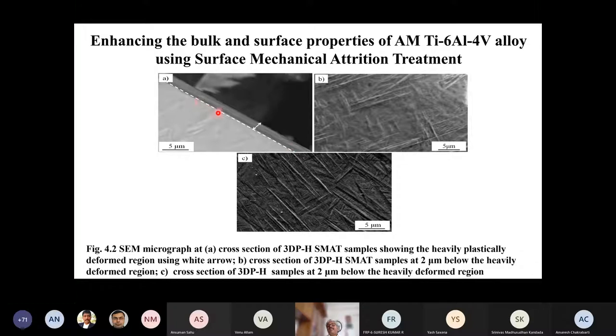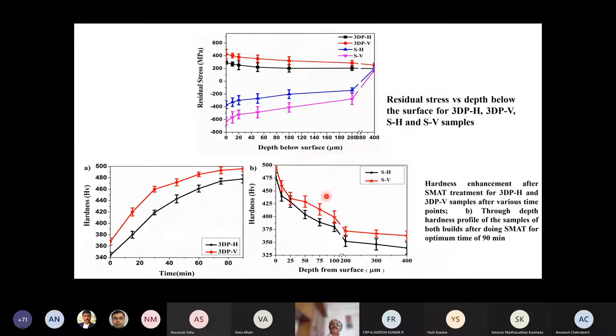And remember that additively manufactured materials are characterized by generation of cracks from the porosities, right? The coalescence of porosities leads to generation of cracks under loading conditions. So in this case, we closed the pores at the surface. Therefore, the cracks which would have generated at the surface were substantially minimized, and this has shown substantially improved properties. So this is the property data here.